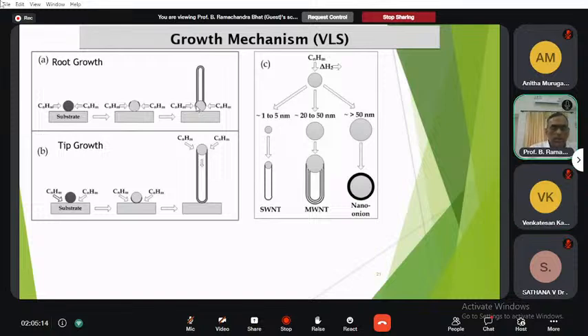Okay. What happens is this CNT precipitation fails to push the metal particle up, and thus the precipitation is compelled to emerge out, as you can see here. It emerges out from the metal's apex, and the carbon first crystallizes out as a hemispherical dome, which then extends to form a seamless graphitic cylinder. Subsequently, hydrocarbon decomposition takes place on the lower peripheral surface of the metal, and the dissolved carbon diffuses upward, thus the CNT grows with the catalyst particle rooted at its base. Hence, it is known as the base growth model.